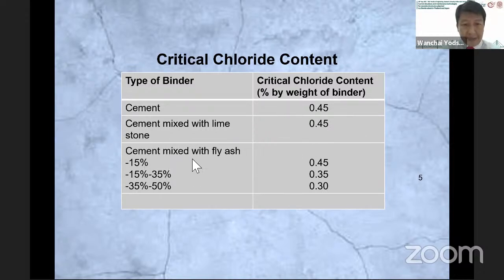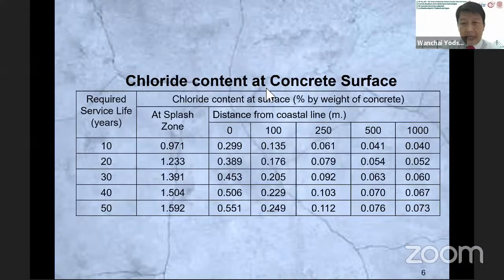And in case of cement mixed with fly ash, it depends on the percentage of fly ash in the binder. For the chloride content at concrete surface, it depends on the required service life of 10, 20, 30, 40, and 50 years, the exposure zone, and the distance from the coastline. So we have the chloride content at concrete surface from this table.